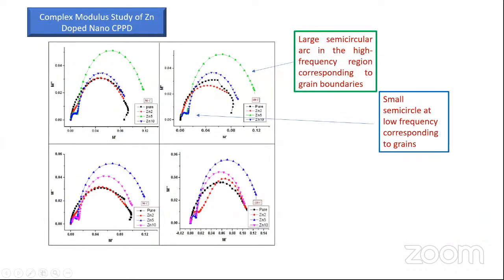Complex modulus studies show that the large semicircle arc in the low frequency region corresponds to the grain boundaries, and the small semicircle at high frequency corresponds to the grain. So there is a grain and grain boundary contribution. In a pure sample, you have only a grain contribution. In a doped sample, you have grain and grain boundary contributions.